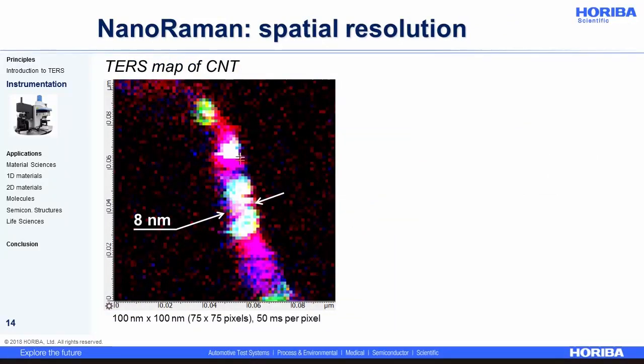The TERS proof is in the image and in the spatial resolution that can be achieved. The figure that you can see here was collected from a TERS scan, 100 by 100 nanometer scanning area, so it is built pixel after pixel. Here of an isolated carbon nanotube deposited on a gold substrate. So the result is a true TERS hyperspectral image with an optical resolution below 10 nanometer. This resolution is obtained with the full width at half maximum of the TERS intensity profile across the CNT.